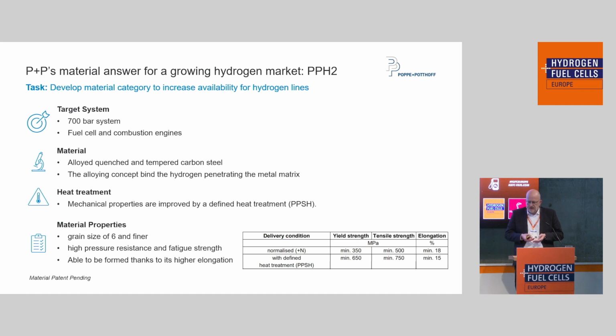The grain size is 6 and finer. We have a high pressure resistance and fatigue strength, and you are also able to form these pipes thanks to its higher elongation. So yield strength is above 650, tensile strength above 750 megapascal, and so PPH2 is a very strong material.